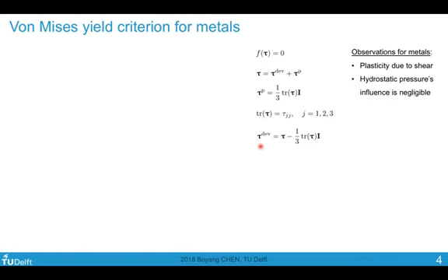For this, a very simple approach is simply to calculate the amplitude of the deviatoric part of the tensor. And when we calculate amplitude, we take the dot product between the tensor and itself. The scaling factor of 3/2 is to ensure that when we have a uniaxial stress state, this whole thing would then return to just the uniaxial stress. So then we revert back to the one-dimensional case. This is the so-called von Mises stress.